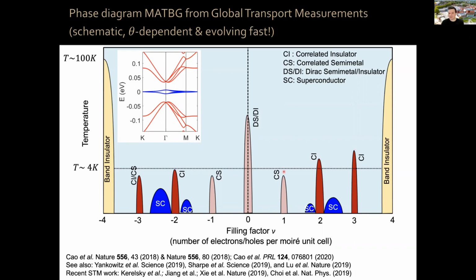And then at 1 and -1, typically you have a correlated semi-metal state. You have a resistance peak quite often at 1, not very present at -1 actually. But this is typically metallic behavior, not insulating behavior. But still, there is an enhancement in resistance as a function of doping here. And then at charge neutrality, depending on a variety of parameters, you can have a Dirac semi-metal or insulator state. All of these things depend on twist angle, also on alignment to hexagonal boron nitride, etc. So this type of diagram has been seen by many people, and the STM work has also essentially seen this.